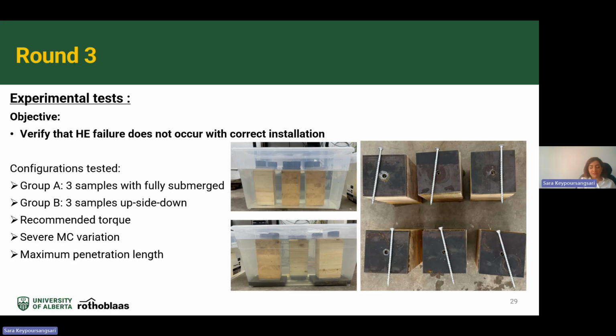And also in this step, we didn't use the load cells because we wanted to increase the penetration length. So here you can see in this picture that there was no failure in self-tapping screws, even under the severe moisture content change.